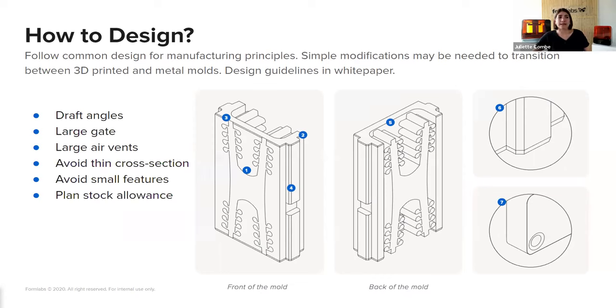Increasing the gate, having a large gate, helps reduce the pressure. Also having large vents for a better flow of the material, avoiding thin cross-sections, avoiding small features. As I mentioned, a 3D printed plastic tool can be much more brittle, in particular for thin features. And also, as you saw in the video right before, plan some stock allowance to help meet both halves of the mold together, just to be able to post-treat the mold rapidly after and have a perfect fit and avoid flashing. So those are some helpful recommendations that will optimize your design. Besides that, there is not much difference between how you design a mold for metal tooling compared to 3D printing tooling. You can incorporate ejector pins, you can incorporate side action cores, and so on.